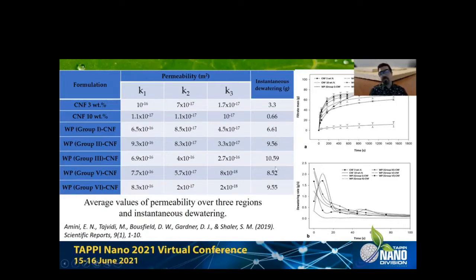When you go to smaller particle sizes or higher surface area, what actually changes is this instantaneous dewatering. As you see, from about 3.3 for 3% solid CNF and 0.66 for the 10% solid CNF, you get to values about 10 grams, which is much faster dewatering. And you can see that in the rate of dewatering also here.